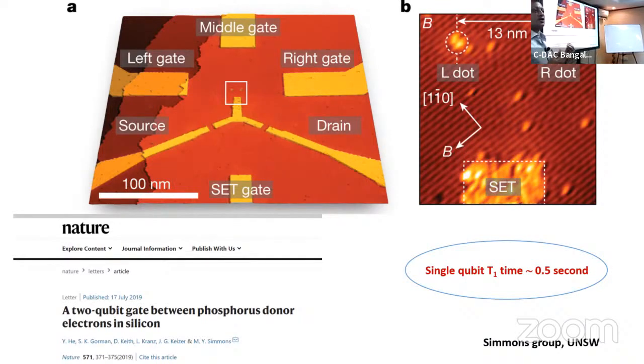Now these are quantum dots, and the phosphorus essentially has spins, and those two spins interact with each other, and you can make the exchange interaction as a gate, and the state of the qubit is given by the spin. And you can see these gates out there. You can use these gates to change the exchange interaction, and you can show two qubit gate operations and so on.